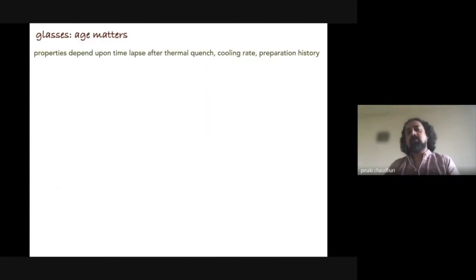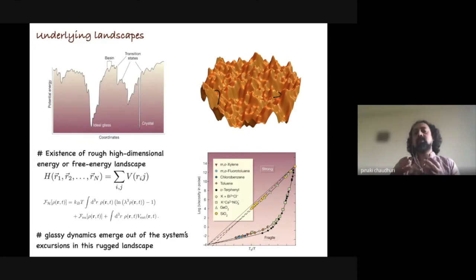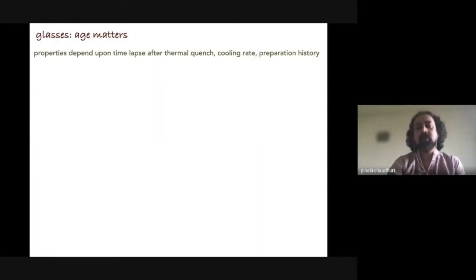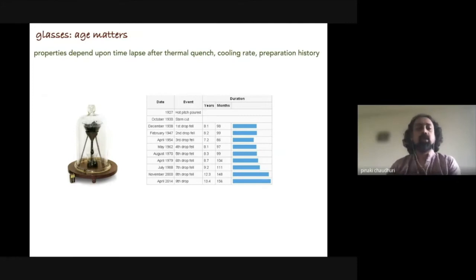So in glasses, if I'm trying to reach equilibrium states, what I'm trying to do is reach these local minima in this high dimensional landscape. In this process, there is an idea called aging, that properties of the glass depend upon the time that has elapsed since you did a thermal quench, or cooled the system, or some preparation history. There's a classic experiment going on somewhere in New Zealand, where tar is flowing out of a funnel, and they count the time between two such drops of the tar. The experiment started in 1927, the first drop fell in 1938, and the ninth drop fell in 2014.